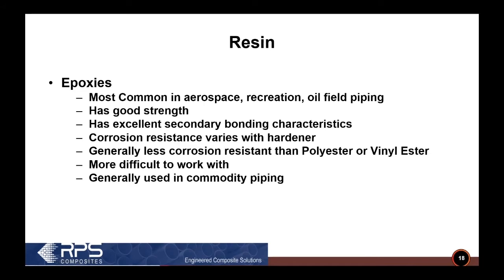That's why adhesives, if you go to the dollar store or Dollar General and you get a little 2 tubes of adhesive that come together, it's actually epoxy. It's an epoxy resin and it's an epoxy hardener. The corrosion resistance of epoxies are generally not comparable to the vinyl esters and polyesters and are very dependent on the hardener that's used. And the hardeners and epoxies are actually made by different companies. So it's a little bit more complicated to get the corrosion resistance of an epoxy.